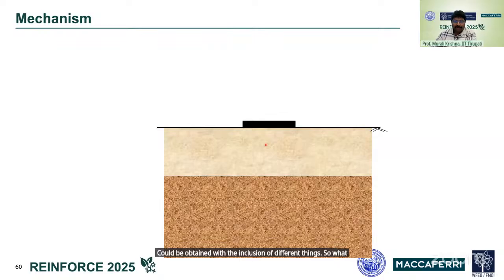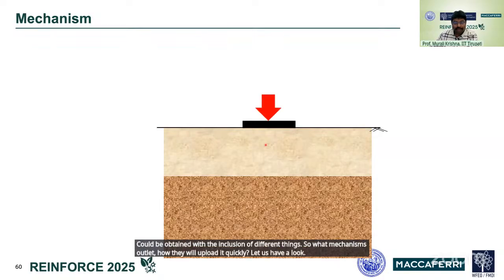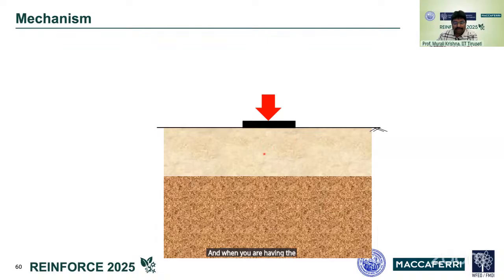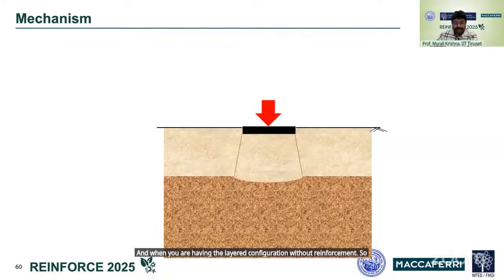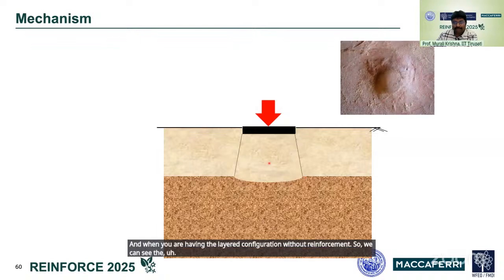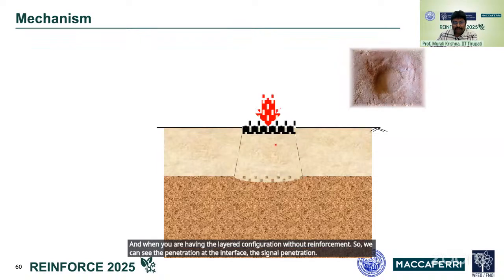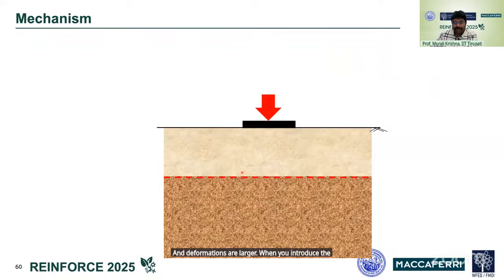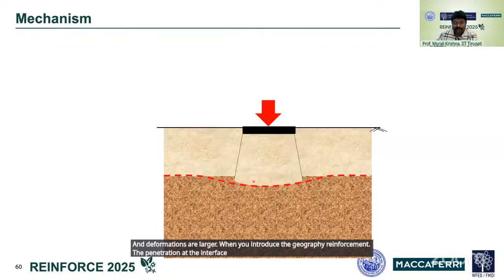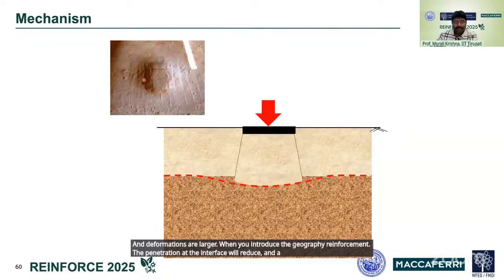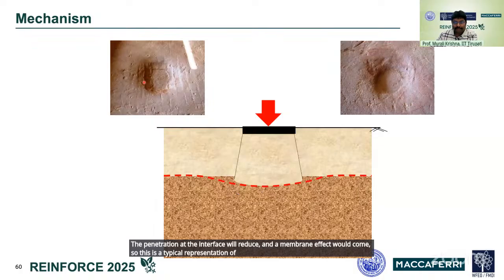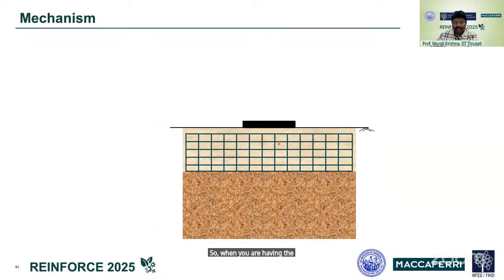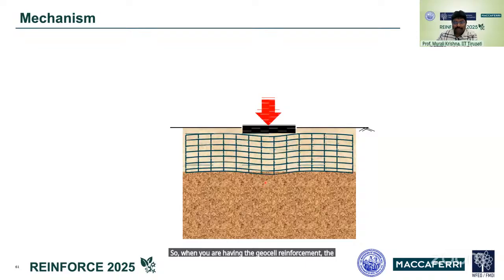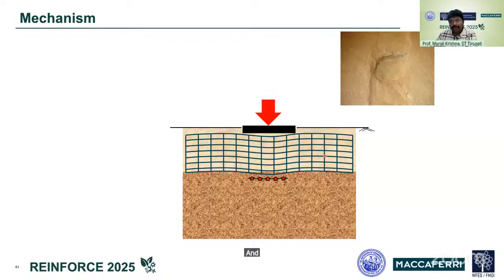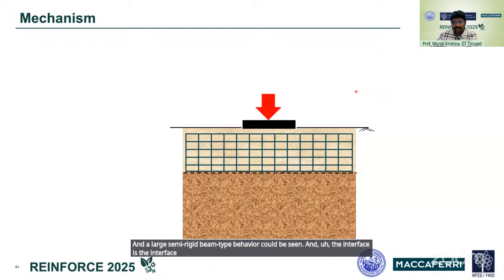So what mechanisms operate, how they will operate, quickly let us have a look. When you are having the layered configuration without reinforcement, we can see the penetration at the interface, a significant penetration, and deformations are larger. When you introduce the geogrid reinforcement, the penetration at the interface will reduce and a membrane effect would come. So this is a typical representation. When you are having the geocell reinforcement, the penetrations would be much less, and a large semi-rigid beam type behavior could be seen, and at the interface you can see much less deformation.